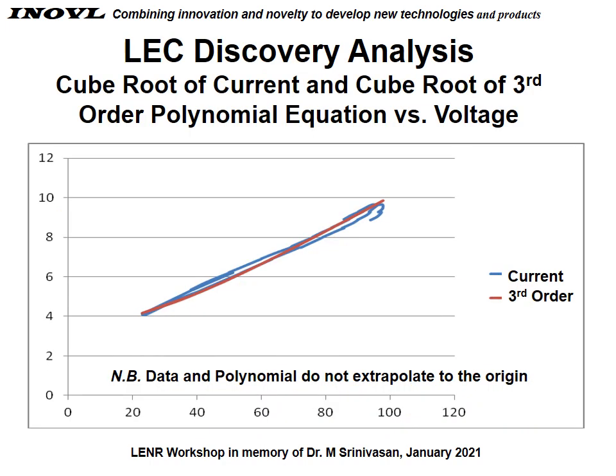Here's a plot of data where we took the cube root of the current and the cube root of the third order polynomial equation versus voltage. And you see they line up pretty close together. The important thing to note here, however, is that this curve does not go to zero when we have 0 volts. That was surprising to us.